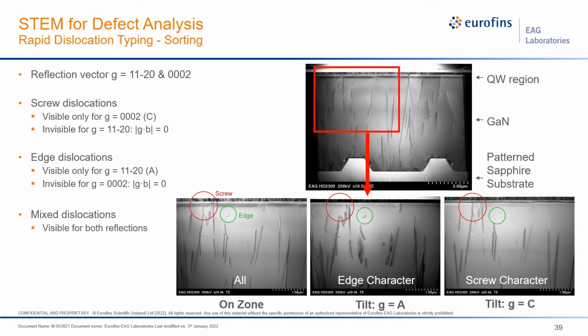And actually notice here, this defect is missing from the edge tilt, whereas it appears here in the screw tilt. So we can actually identify this particular defect as screw only. And this is the opposite for the defect here. It's missing in the screw, but it's present in the edge. So we know that this is a pure edge defect here. Whereas the majority of the defects are actually mixed. They appear in both tilt situations.